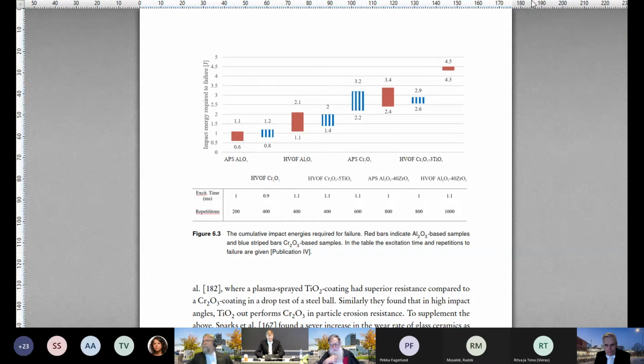Okay. So if my understanding is correct, the impact energy is almost like a fracture toughness. In a sense, yes, but it's first repetitive, so with up to 1,000 repetitions, and with the spherical indenter, which makes the big difference that it's not meant to cause a crack. Okay, so let's just assume that it might be an accumulative fracture toughness. Are we talking about mode 1 or mode 2? Are we talking about tensile or shear with regards to the crack propagation direction?